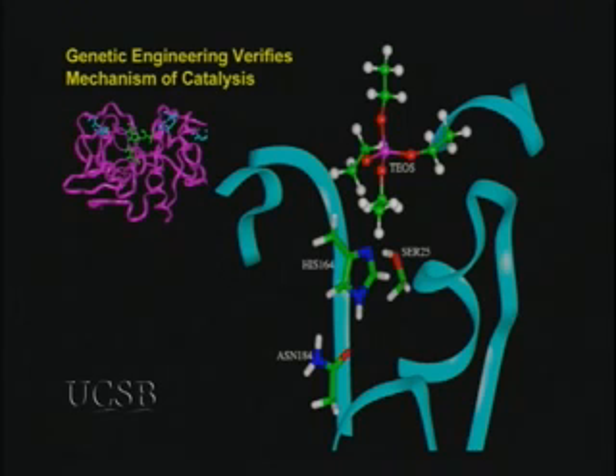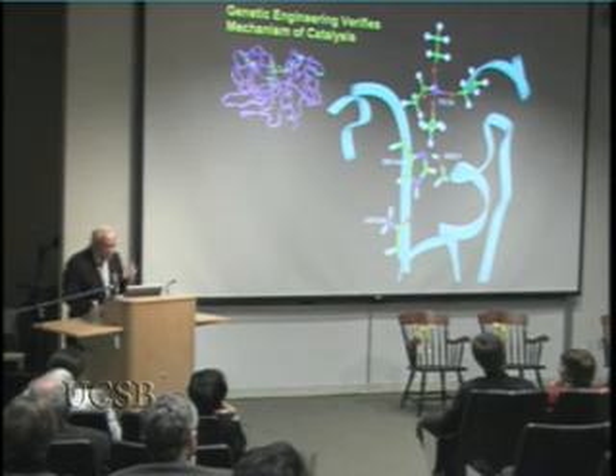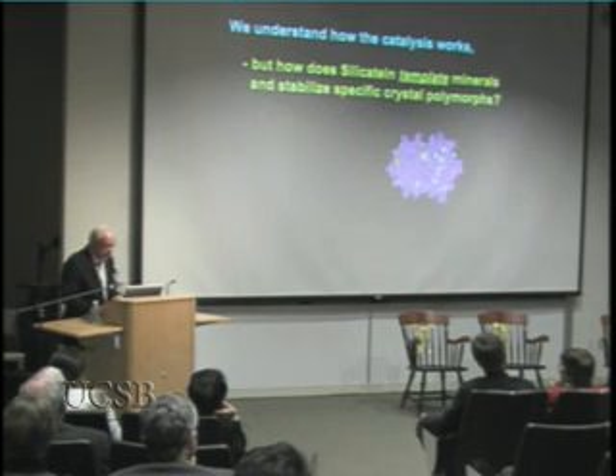And with this approach, we found that, in fact, the 3 amino acids that are identified here are required for the catalysis of synthesis of silica glass from the molecular precursor that's shown here. And of these 1, 2, 3 side chains, these 2 are the most essential. If we knock them out, we knock out the catalytic activity.